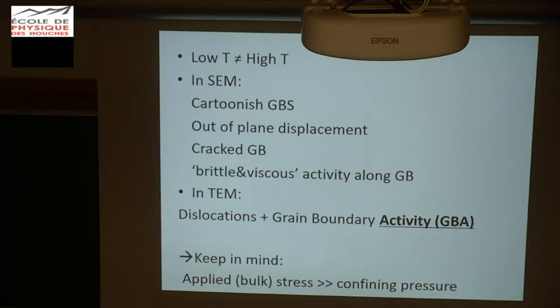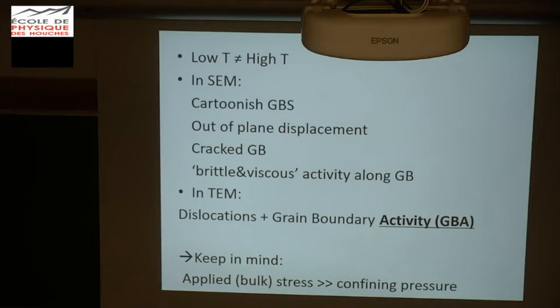So, what do we have? We have low temperature which is different from high temperature. SEM seems to be quite important — we cannot base our conclusions only on EBSD and MTEX. In SEM, we get even some very cartoon-like evidence of grain boundary sliding. We have this out-of-plane displacement, which can be related to relaxation after deformation. We see cracked grain boundaries — it's something between brittle and viscous activity along the grain boundaries.